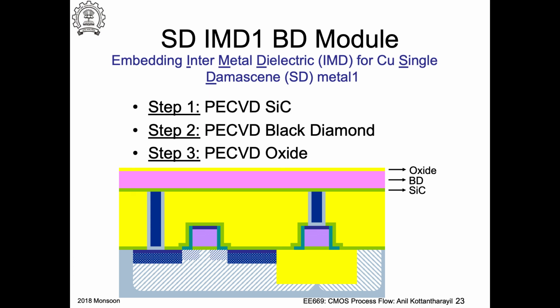Okay, so you need to put more metal layers on top, right? So you continue like this. You deposit, in this particular case, a PECVD silicon carbide layer. Okay, and then you deposit what is called black diamond. This is actually a proprietary technology by a company called Applied Materials. Black diamond is nothing but an amorphous carbon film, and the advantage of this is that it has a low dielectric constant of 2.2, and also the silicon carbide provides a very dense diffusion barrier.